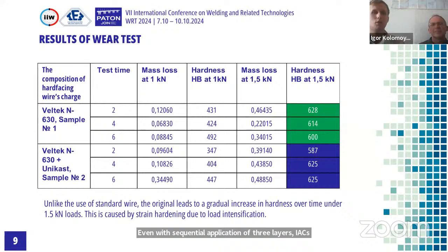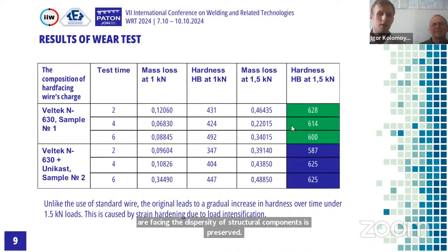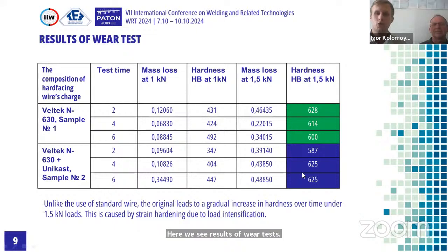Here we see results of the wear test. Unlike the use of standard wire, the original leads to a gradual increase in hardness over time during 1.5 kilonewton loads. This is caused by strain hardening due to load intensification.